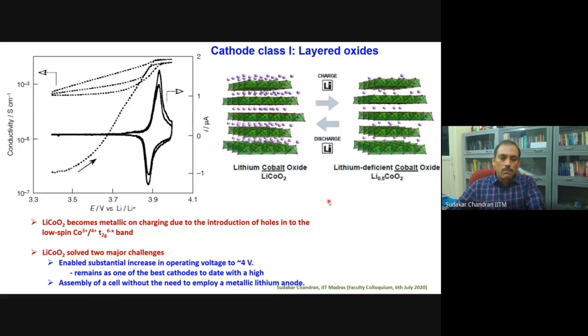In Goodenough's group, when he was working on inorganic solid electrolyte compounds, oxide-based compounds, and then after the titanium disulfide work, they were looking for two problems. One problem is to replace the lithium metal anode with an intercalation compound, and the other one is to replace the cathode with a high voltage material. So this particular discovery enabled increasing operating voltage. And the other problem is that the titanium disulfide doesn't have lithium to begin with, whereas this compound has lithium to begin with, which means when you assemble the battery, this compound is in a discharged state, whereas the titanium disulfide is in a charged state. The batteries made using titanium disulfide cathodes are in charged state, which gives a lot of engineering related problems to assemble the batteries. So this particular compound was very useful.